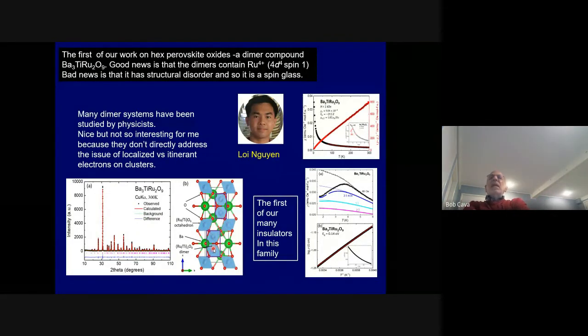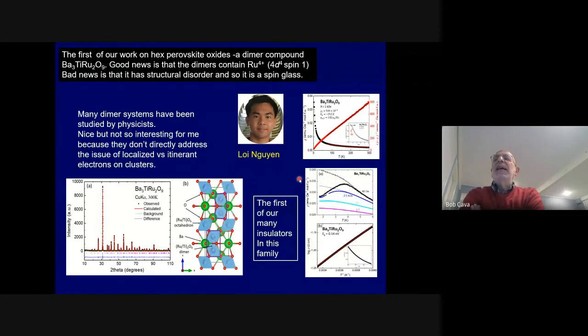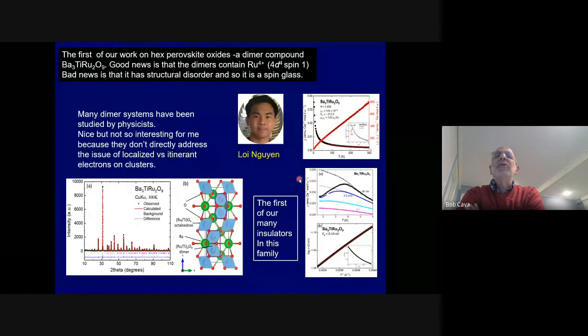And now when you look at the magnetic susceptibility of this thing, you can see that it has a finite Curie-Weiss theta, 29 Kelvin. So that's good. And ruthenium has unpaired electrons. But the bad news, as far as I'm concerned, is that this material is a spin glass. And that's because titanium and ruthenium are so similar to each other that we get a measurable amount of disorder, where we have some ruthenium on this site and some titanium on this site. So the net result is we don't have good chemical ordering between the dimers and the isolated octahedra.